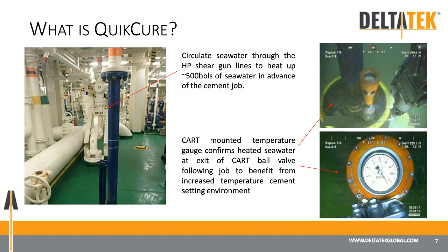Now, in the 6, maybe 7 jobs that DeltaTek have done with the dart, the first 2 resulted in the cement dart being lodged in the cement head. This is an age-old problem around our industry. However, with the DeltaTek design review of the dart, in the subsequent deployments we have experienced 100% success. However, the recommendation from DeltaTek is to go with the ball, on the basis that there has never been a failure with the DeltaTek ball, and 100% success has been achieved. Further, it's much simpler to use the ball than a dart, and the benefit of the QuikCure is a nice feature as well.